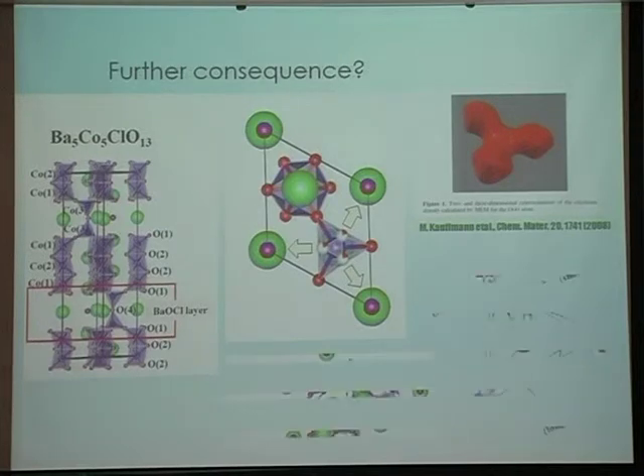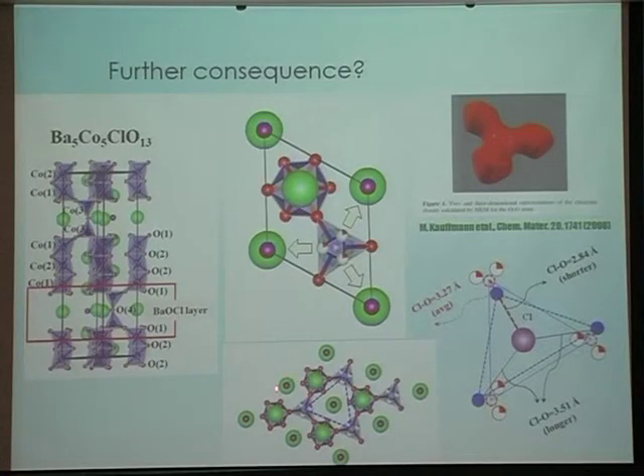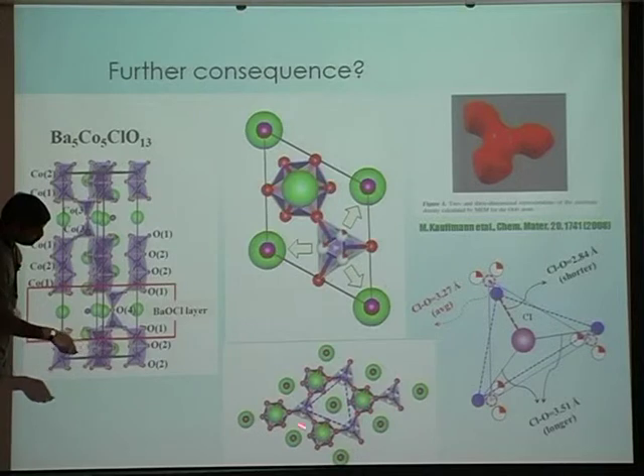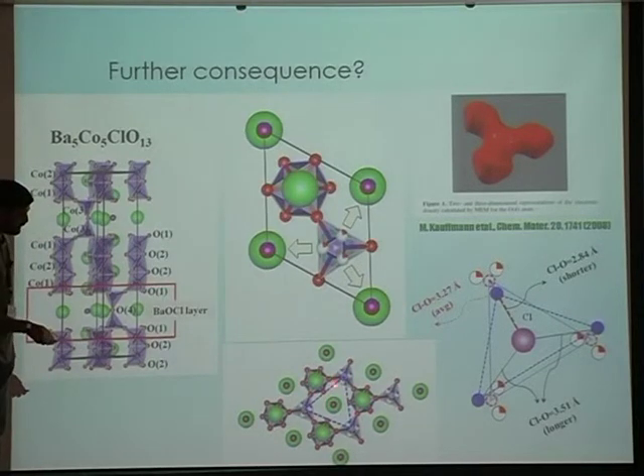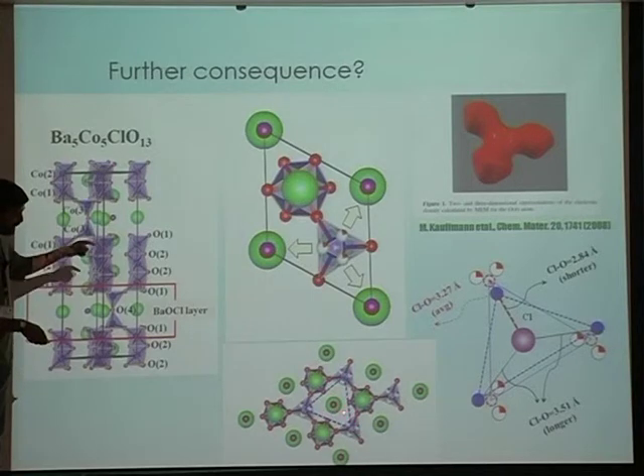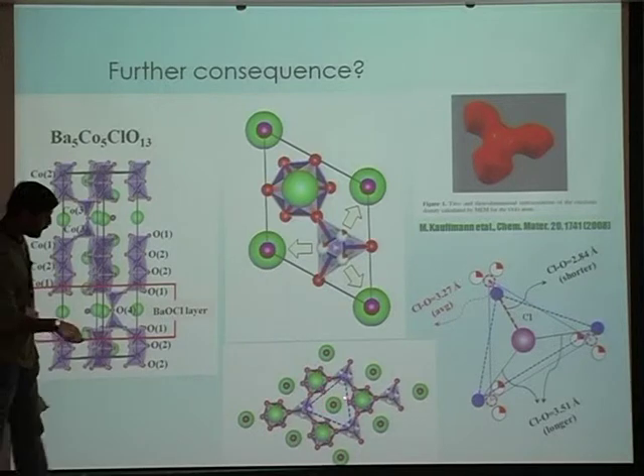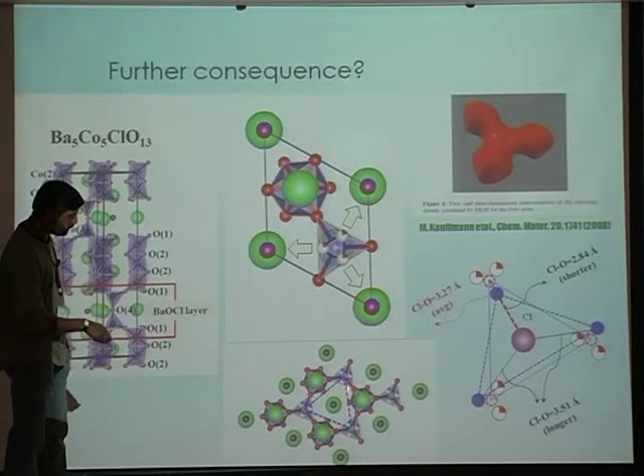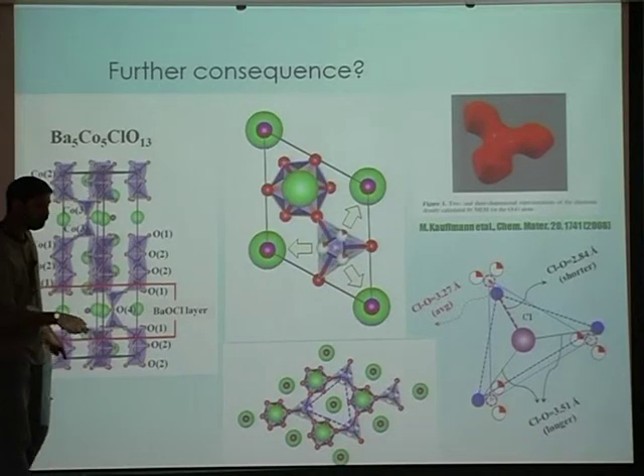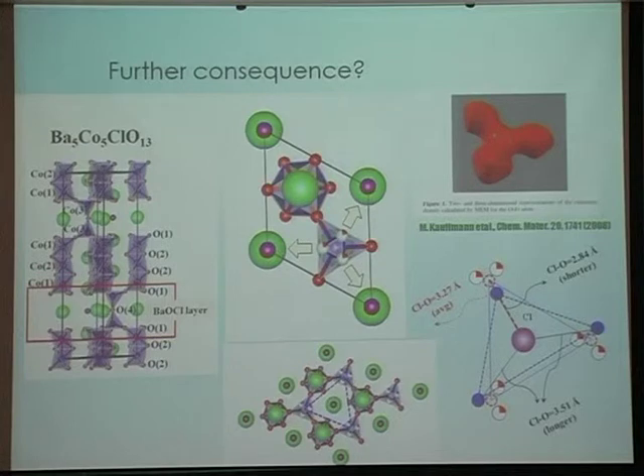Now, when we do the EXAFS, there is an advantage. What we are doing is chlorine EXAFS. That means we are looking at the region around the chlorine. Now, if the positioning of the oxygens is static, then chlorine will always find an asymmetric triangle around it, unlike this symmetric triangle. These are the 3 oxygens possible. So by EXAFS, I can find out whether this distortion is static or dynamic. If it is dynamic, it will still find 1/3, 1/3, 1/3. And EXAFS says it's static. It's static within the experimental time scale of EXAFS.